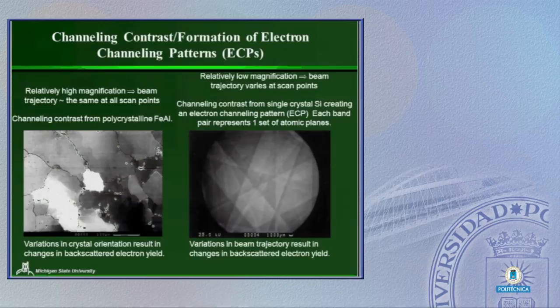If we take a single crystal of silicon, so now the orientation remains the same, but we look at that at very low magnification. As the orientation of the beam changes as we image a sample, and that's effectively what happens in an SEM at very low magnification, we get a beam raster where the beam orientation changes. We'll get a series of lines that is indicative of the crystallography of the sample.